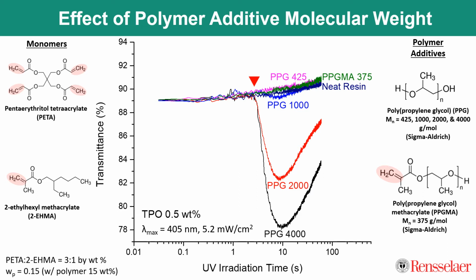concentration. So now looking here, we can see that neat resin, PPGMA, and PPG425 all do not have a decrease in transmittance, but they do have a slight increase over time as the TPO is being consumed. However, as we increase the molecular weight of the PPG additive, we can see that the extent of phase separation becomes more drastic, which shows us that there is a molecular weight dependence on the phase separation ability of the polymer additive in the resin.